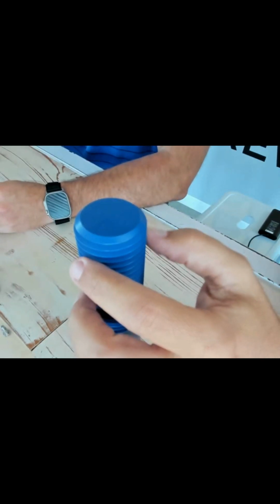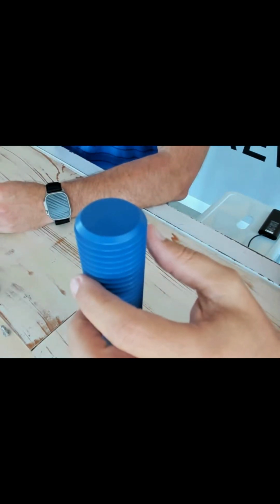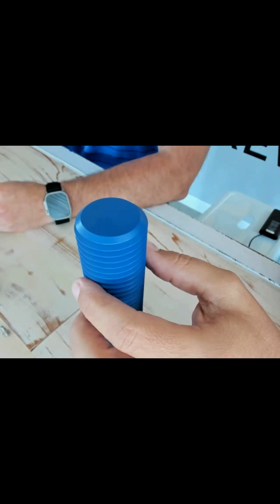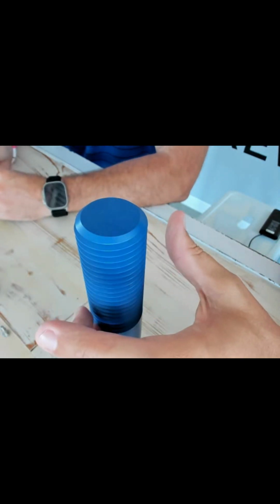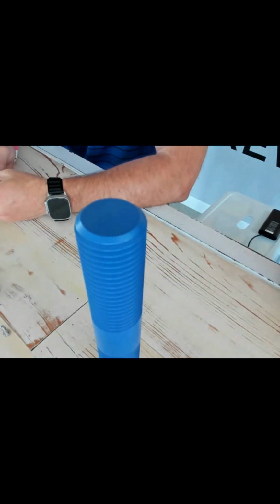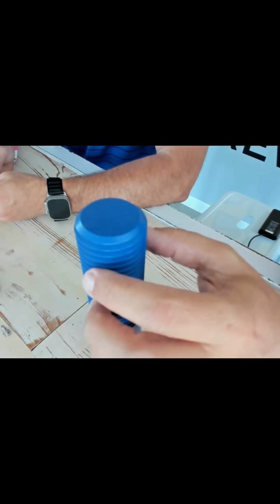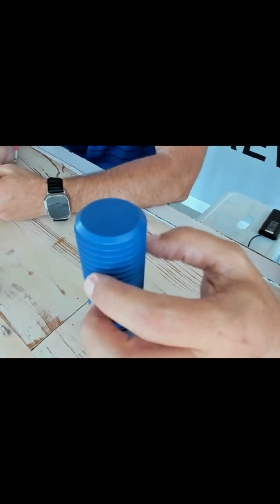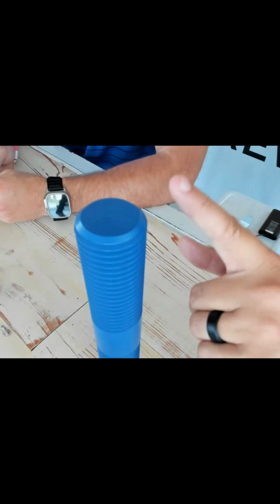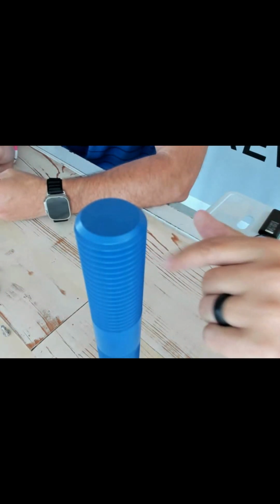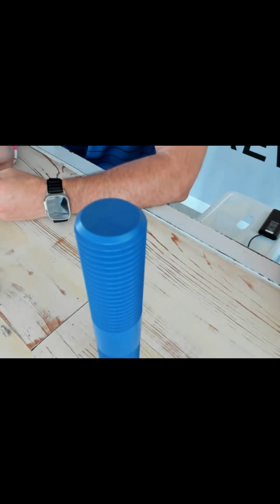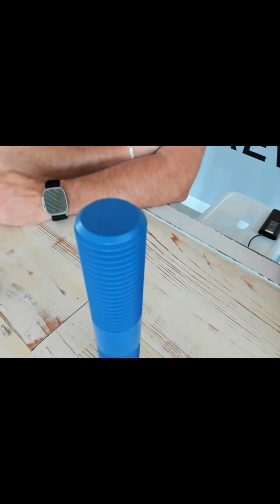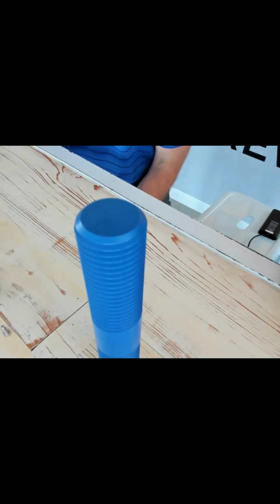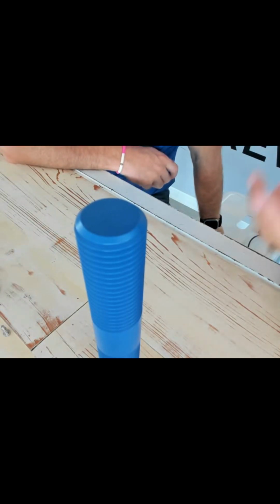Generally the coating with the base coat and top coat is about 0.02 of an inch thick. And when we talk about increasing 10 thousandths of an inch for the overtap, that amount is really what corresponds to allow that 2 thousandths clearance to allow for the coating on both the male thread and the female thread so that it threads together. So especially on some of the smaller diameter fasteners, you have to open up the clearance in order for it to assemble. And so you don't have binding and that sort of thing between the threads.